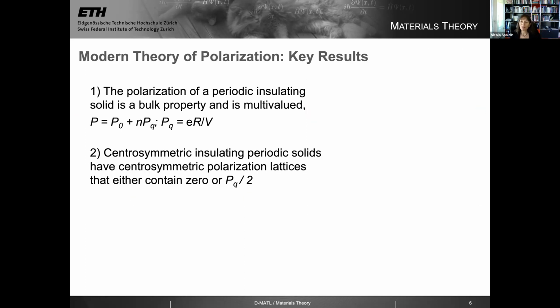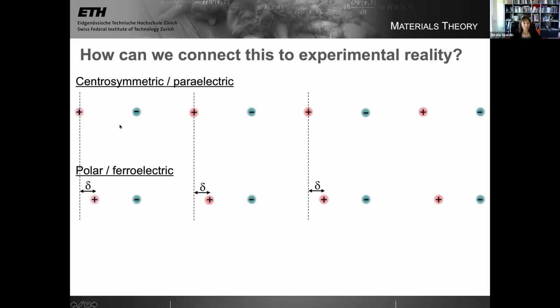Okay, so this might seem a little bit unsatisfactory though, polarization. We like to think it should be a number, a kind of thermodynamic quantity, and how can it be this list of numbers? Let me show you how we connect this slightly abstract behavior to experimental reality. To do that, we should compare our centrosymmetric, paraelectric, non-polar lattice, with alternating plus and minus ions, with the ferroelectric polar case that we looked at first. I've lined these up so that the anions, the negatively charged ions, are above each other. And in the ferroelectric polar case, each cation is shifted to the right to make the polar case.